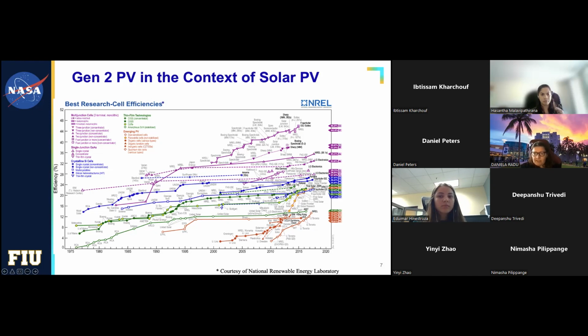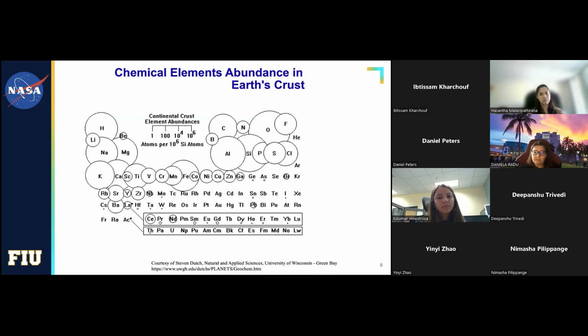The reason I mentioned that is because there are a lot of companies in green here that picked up on CIGS, and then all of a sudden we have this orange here, the perovskite that came in, and there was very little investment in continuing improvements on the CIGS. But the hope is not lost. And there is another reason why people were not that crazy about CIGS anymore, which is about the chemical elements abundance in Earth crust, as I mentioned earlier. So what other elements could be, if you think about